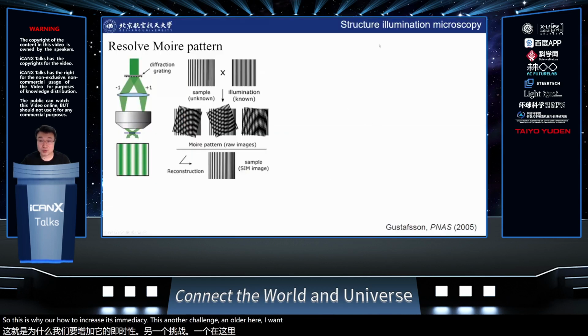And over here, I want to introduce structured illumination microscopy. For this method, as mentioned before, it's based on the beating frequency of the illumination pattern with your sample, and you can also think of this as the moiré pattern, or moiré fringe. If your sample has some unknown frequency, changing from really low to really high, and your illumination is in some other frequency, and you overlap the patterns, you will see the moiré fringe. You will see that in the frequency beating, your larger fringe is going to change. So if you rotate 180 degrees and do lots of patterns, you can finally figure out what your sample pattern is. So this is basically the working mechanism.